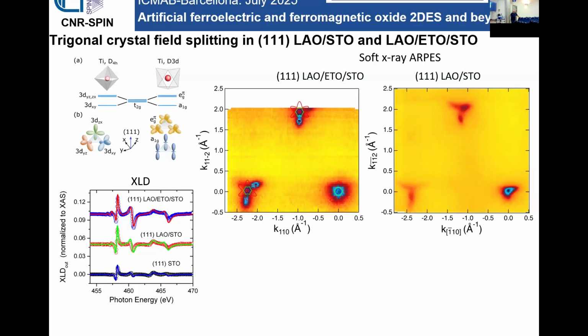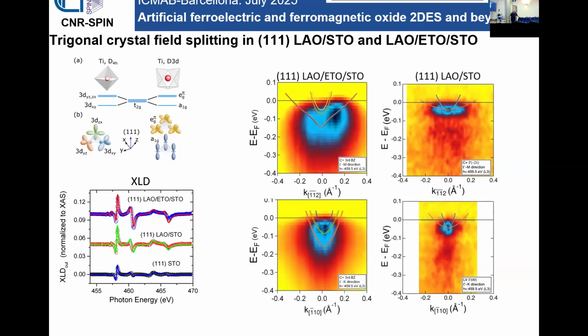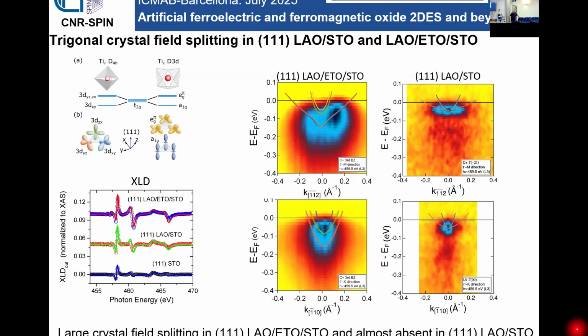More or less, this was also confirmed by soft X-ray angle-resolved photoemission experiments. I will show the band dispersion, which is very different in the case of 111 LAO/ETO/STO, where we see a clear trigonal crystal field splitting between these two bands, while in the 111 LaO-STO the splitting is very small, so it is very difficult to really work in a regime where only one band contributes to the transport. So I would say that, while very interesting, the published results on 111 LaO-STO, for sure, their interpretation requires the inclusion of multiband effects, because for sure more than one band is at play.